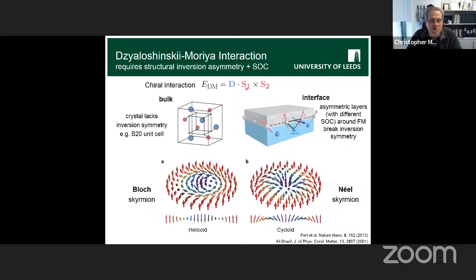This DMI was proposed by Dzyaloshinskii and Moriya several decades ago, and was used in various more exotic corners of magnetism. But it turned out to be really important in stabilizing these Skyrmions, and now it has found its place in magnetism and is very widely studied. So it requires 2 things. You need a spin-orbit coupling, and you need an inversion asymmetry in your material.